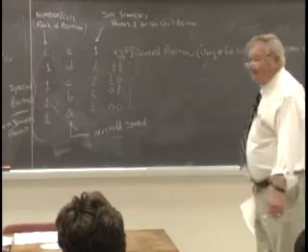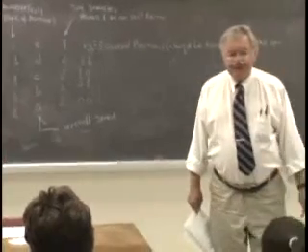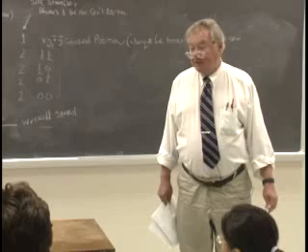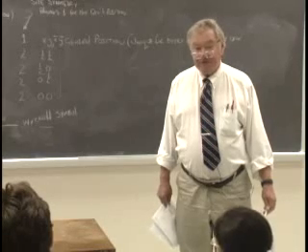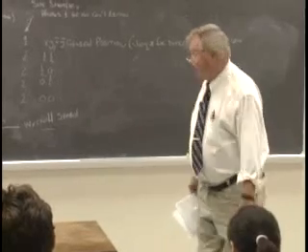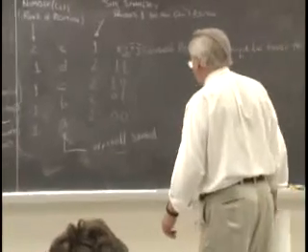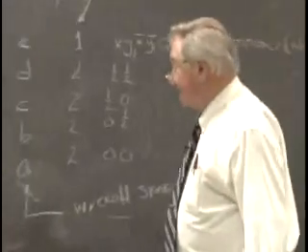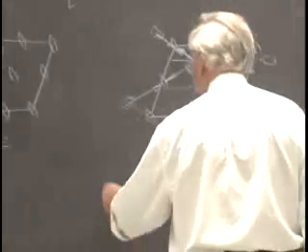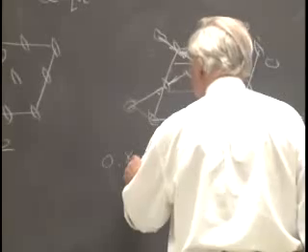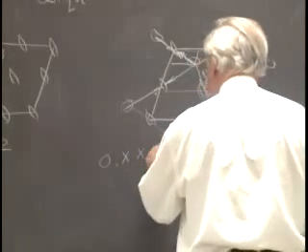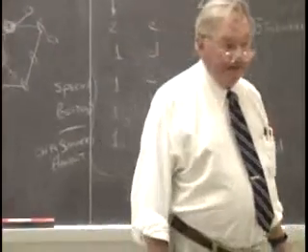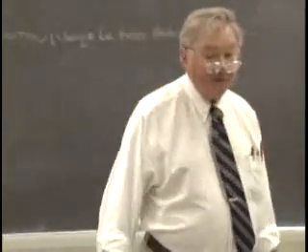Okay, so this, my friends, is the language in which you will see structural data cited when people have determined, using diffraction methods, the locations of all of the atoms within the unit cell of a particular material. If the coordinate is variable, with today's techniques and high-speed computation, you can get x as a fraction of a cell to usually at least plus or minus 1 in the 4th place. So it's data that can be determined extremely precisely.